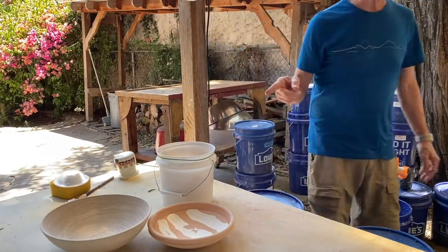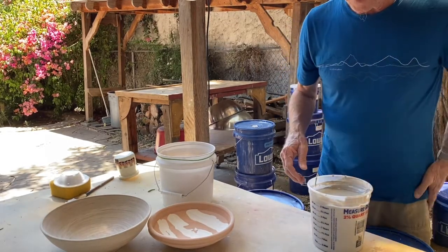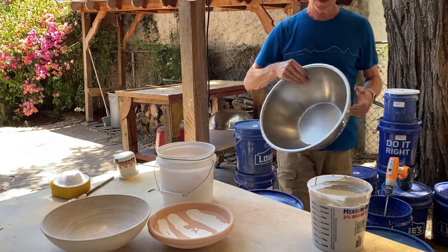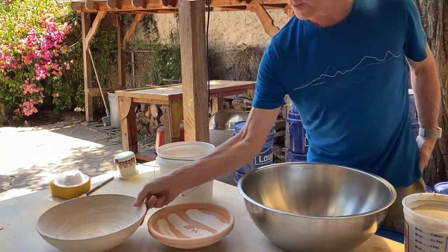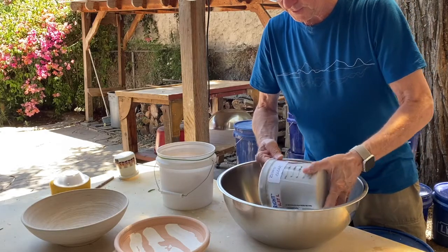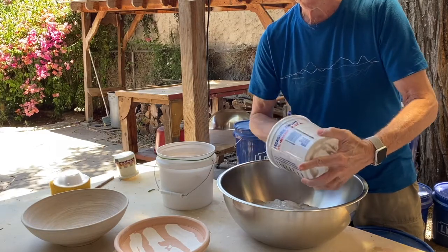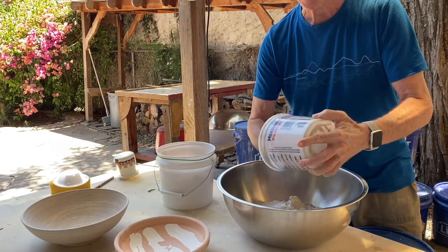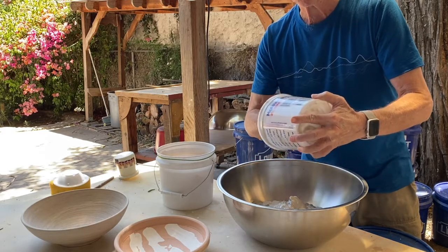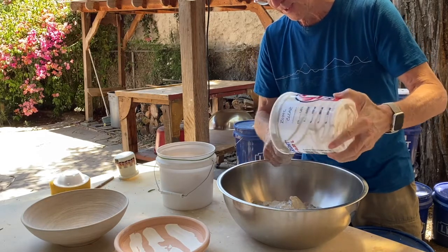Okay, I'm gonna glaze these couple pots with a clear glaze. And it's actually an experimental clear. It's a glaze that I've used, the base glaze that I've used with cobalt in it. But I'm gonna try it here just by itself. As the base, it's a simple glaze. It's just Gerstley borate or colemanite and feldspar. I don't remember the exact percentage, something like 70 to 75% feldspar, I think, and the rest Gerstley borate.